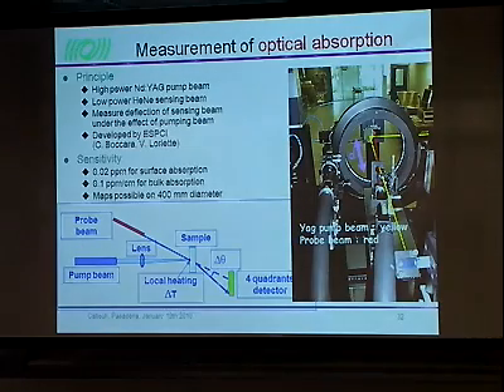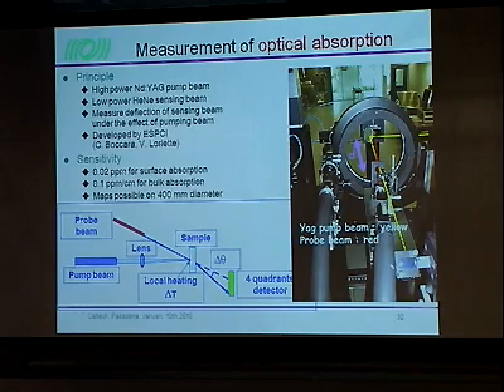We have several tools to test these coatings. The first one is for the measurement of the optical absorption. It's based on the thermal deflection of a low power beam which goes across the coating, which is heated by a high power neodymium YAG beam.